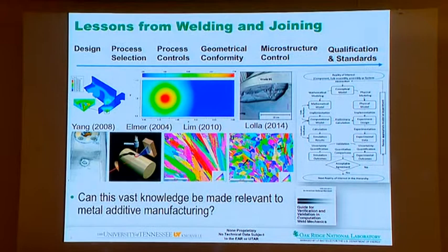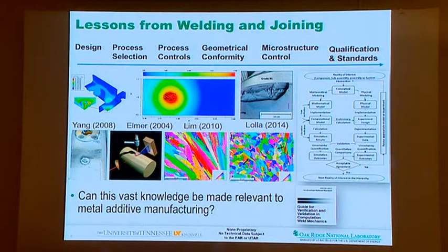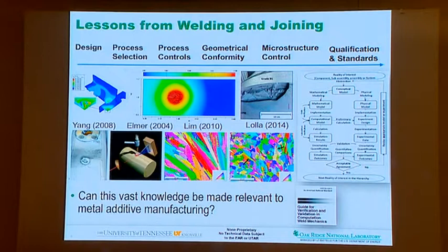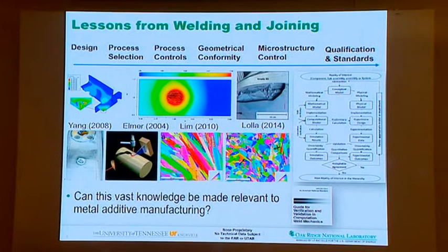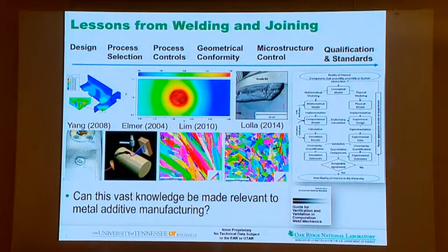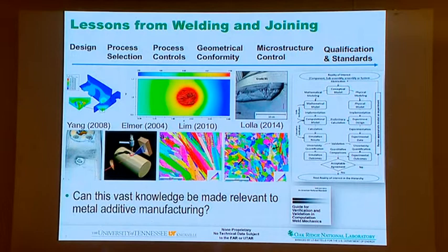In addition to that, we also do process modifications, and that simulation for a gas tungsten arc welding with the magnetic field, we oscillate it, and then we can kind of churn the melt pool, and then those black lines you're seeing are computational fluid dynamics vectors, and with that you can actually describe what is happening at the boundary between liquid and solid. So my metallurgy students and friends, you should know that when you change the liquid-solid interface, you can either get columnar grain structure or equiaxial grain structure, and that is one of the things about welding too.